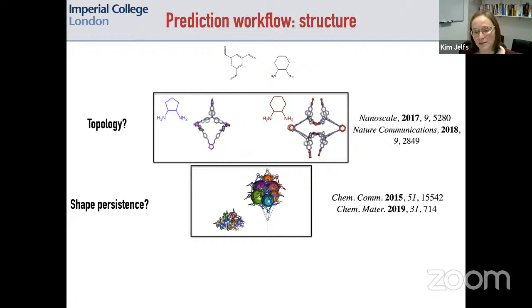And the lack of shape persistence is what explains the lack of porosity in the top right molecule that I just talked about. In the absence of solvent, each of those vertices folds inwards and removes your internal cavity. And largely it's due to too much flexibility in that system. And in fact, the solvate structure, which is the one that I'm showing at the top right, has within the crystal structure maybe something like 260 different DCM molecules that would be sitting somewhere within that cavity, scaffolding it to be open. But in the absence of that solvent, it loses all porosity.